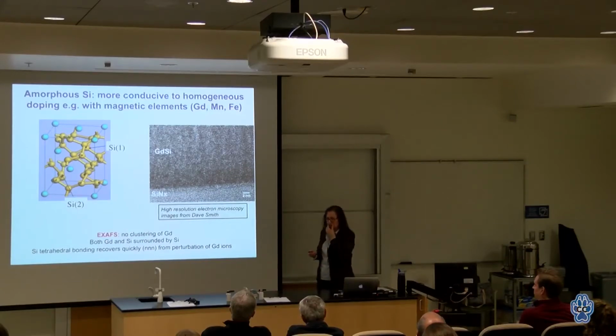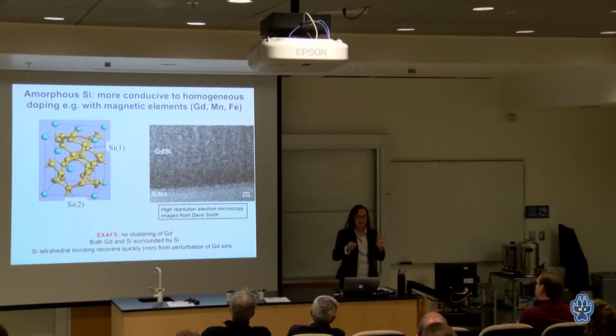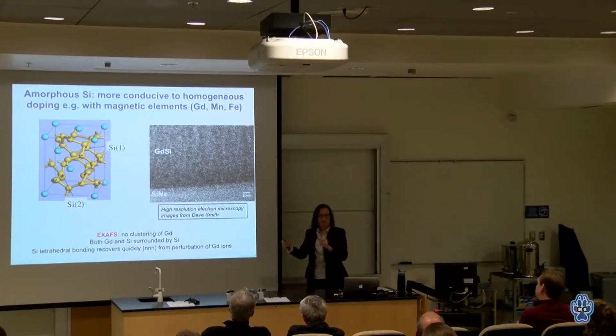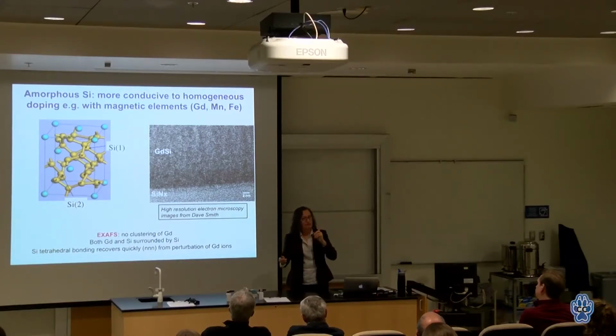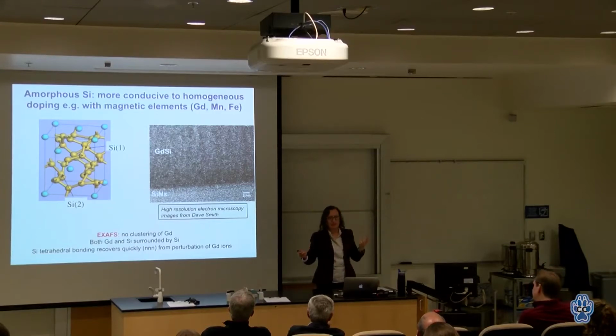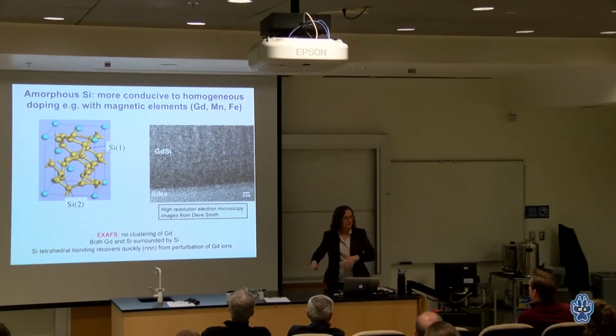One of the things that happens is the electrons are suddenly occupying singly occupied states. Usually the electrons always end up in these paired states, one spin up and one spin down. At that metal insulator transition, they occupy single states. And because of that, they have a spin. They are now magnetic. They're not really ferromagnets, but they have a magnetic moment. So I'm a magnetician. This was an interesting idea that you could take something utterly non-magnetic and suddenly make it look magnetic because of this odd effect that happens at the metal insulator transition.